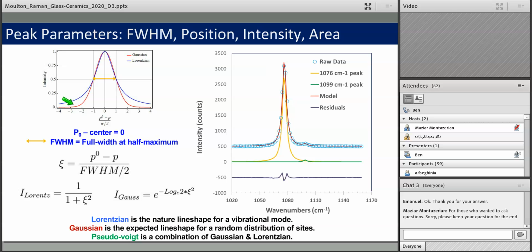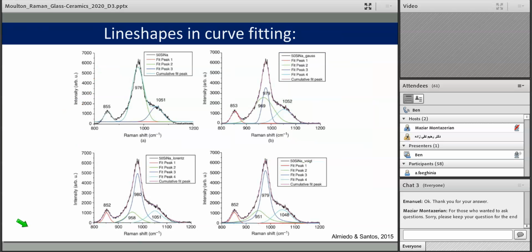These are the formulas for how the intensity decays as you move away from the center. And just to say that if you have a pure crystal, you should be using Lorentzian line shapes because they accurately describe the photon-phonon interaction probability. The other alternative that's very commonly used in glass literature is Gaussian line shapes. This would be expected if there is a random distribution of similar Lorentzian line shapes in the spectra. What's becoming more in vogue is the pseudo-Voigt line shape, which is just a combination of both the Gaussian and Lorentzian line shapes. There are many other line shapes that you can use, but I opt for simplicity because all of these other line shapes have more model fit parameters, and therefore you can mislead yourself into believing you have a better fit than you do.